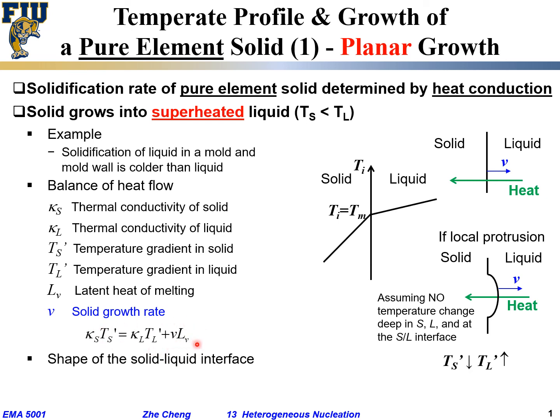In order for this equation to remain balanced, and L_V is positive, the only way is for the velocity to decrease. Again, on the left side, the temperature gradient in the solid decreases because the distance gets larger while delta T is the same. Okay, delta T over delta X is the temperature gradient, and it gets smaller on the left side. On the right side, for the same reason, the distance gets smaller while the delta T is the same. So T'_L within the liquid phase gets larger. T'_L gets larger, so the first term on the right side gets larger while the left side gets smaller. In order for it to balance, the only way is for the velocity to decrease.